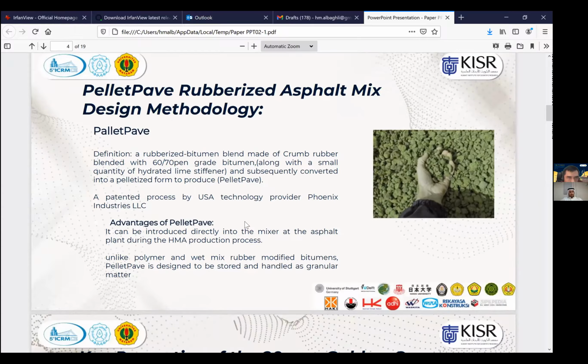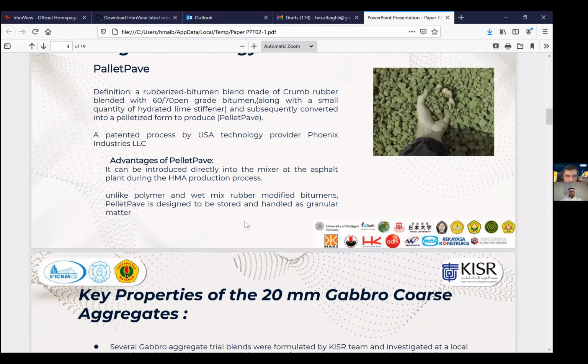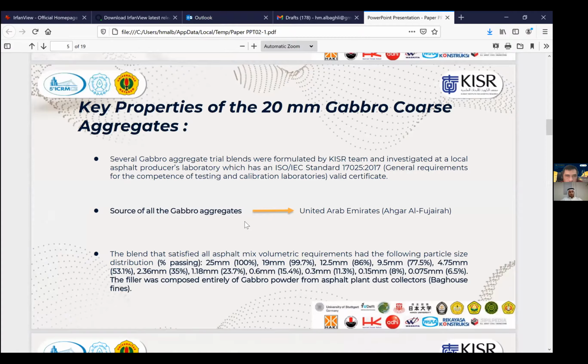We also formulated several gabbro trial blends. The source of all gabbro aggregates was the United Arab Emirates, and the properties of all coarse and fine aggregates satisfy the new Kuwaiti specifications that I mentioned earlier. The design gradations were all in compliance with Type 3 wearing course hot mix asphalt, with a nominal maximum aggregate size of 19 millimeters.